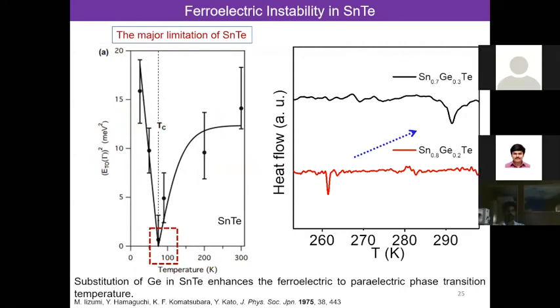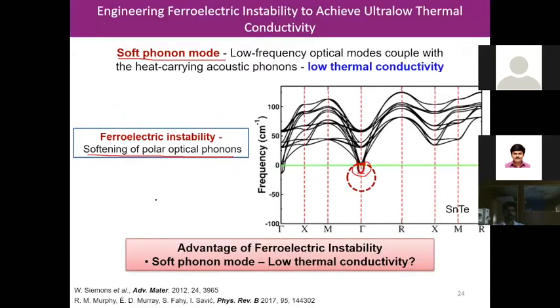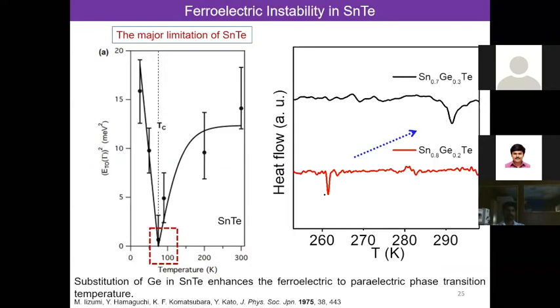So now we ask the question: can we combine these two fields, ferroelectric instability and low thermal conductivity, to have a high ZT? Because these two fields are connected through the soft optical phonon. That was the idea, and this is more of a fundamental intrinsic parameter. You can play around with bonding and structure in this. So in order to do that, we purposefully dope germanium around 20 to 30%. Once we put in germanium, the ferroelectric TC turns out to be near room temperature, as seen in this DSC curve. This is 30% germanium doped in tin telluride.